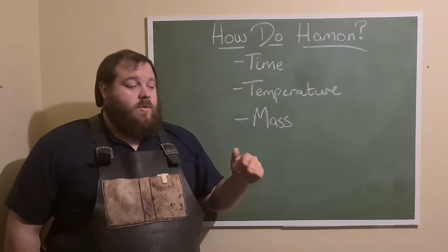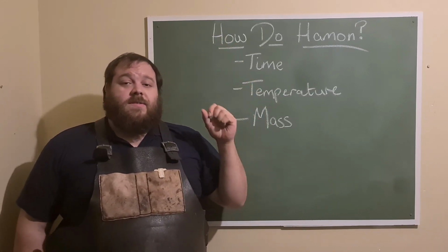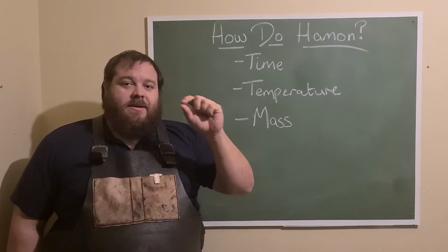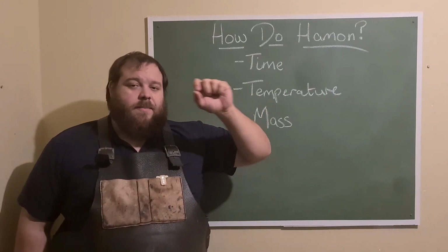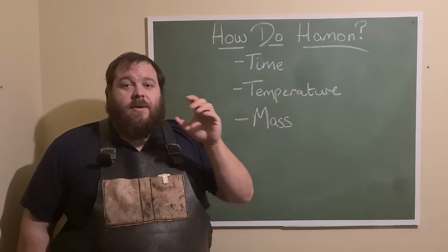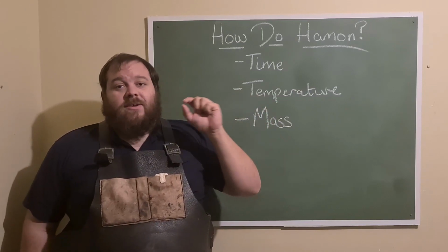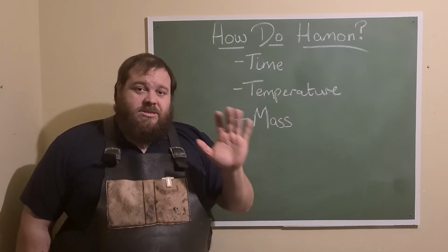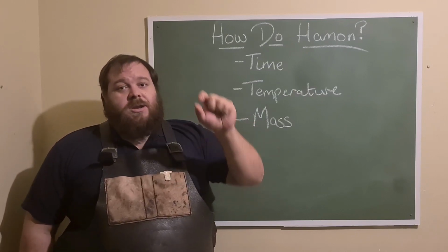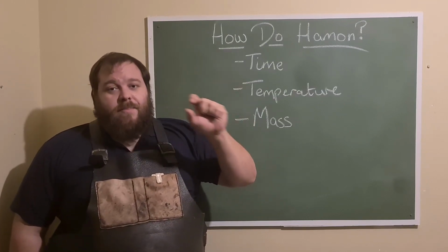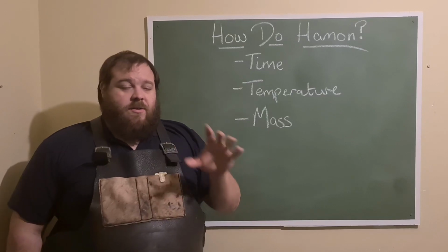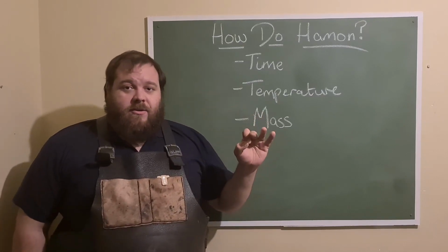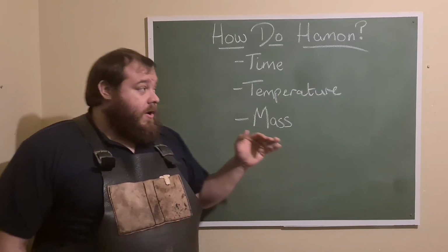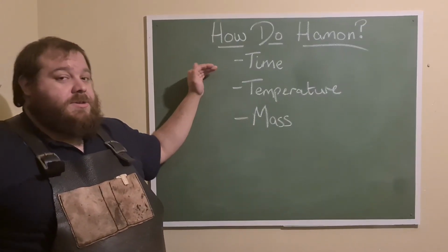Because what we're trying to avoid is grain growth, because the smaller the grain, the better defined our Hamon line is going to be. Because, again, we're trying to see the grain. All we're seeing when we etch the steel is the variation in grain between ferrite, pearlite, and martensite. So therefore, the finer the grain, the better the Hamon. So the time at temperature is going to be really important.